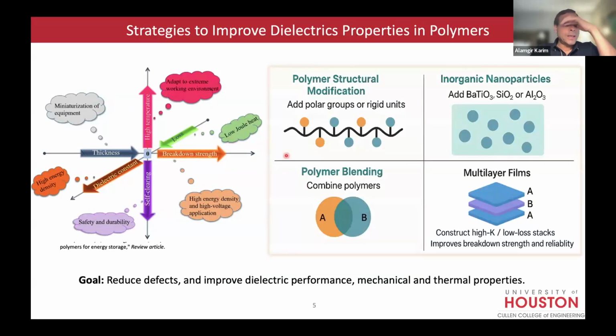And people have tried in this area a lot of strategies. They've modified the polymer. This is by far a huge effort. Blend polymers to combine the best of two properties. Add inorganic, and this one, as I said, the main idea was to enhance the dielectric constant. Barium titanate has very low breakdown voltage, but extremely high dielectric constant. And then multi-layer films is sort of the latest theme.